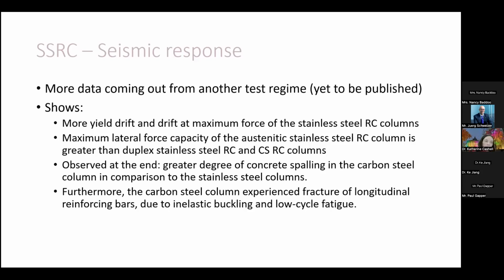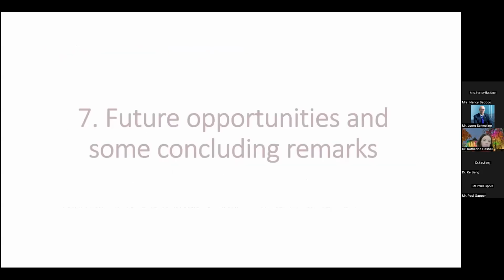At the end of the test, it was observed that there was a greater degree of concrete spalling for the carbon steel reinforced concrete member compared to the stainless steel member, but this needs a lot more investigation. And the carbon steel column experienced fracture of the rebar, which obviously isn't particularly wanted, due to inelastic buckling, and that did not occur in the stainless steel reinforced concrete member. So there's some very positive results there, which need a lot more exploration, but the early signs are that this can provide a really nice solution.